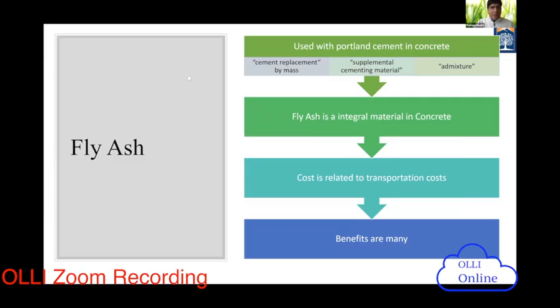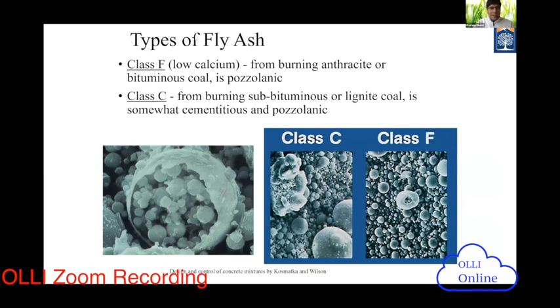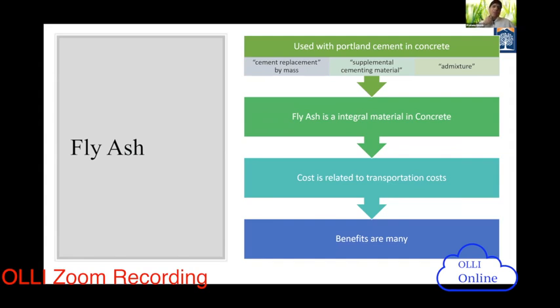Let's see the next one. Just to show you the picture, the left side picture is the cement particles. You can imagine cement particles have a bigger particle size compared to the fly ash picture. That's one of the things I need to mention. When fly ash is used in combination with cement, the cement replacement is done by mass. So it can happen, for example, that we use 80% cement and 20% fly ash.